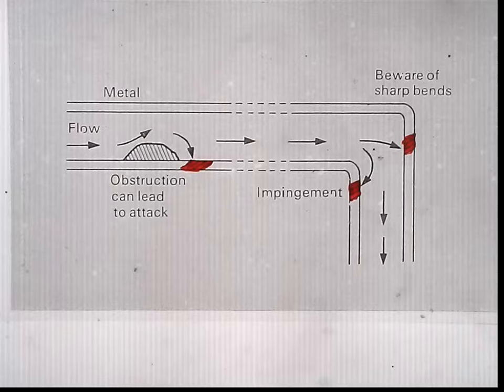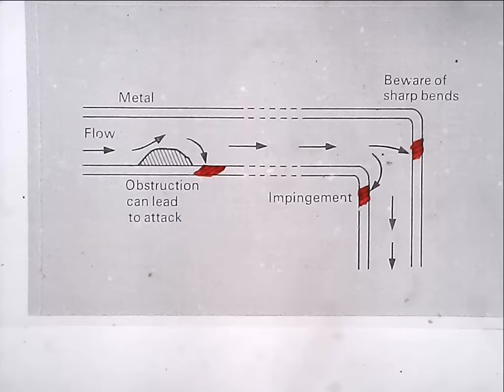If the root of the weld is sticking out, then as the flow comes round, it'll impinge. So these impingement sites are important to consider, and that means the quality of your fabrication in terms of getting good root penetration, but not so much weld material that you've got loads of bumps on the inside of this pipe every time you've got a joint, is quite important.